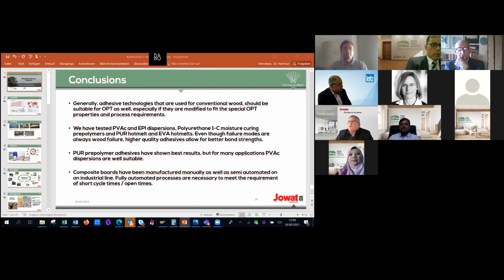So coming to my conclusions, generally, all adhesive technologies that are used for conventional wood should actually be suitable for OPT, as it is chemically a similar material. And this is actually the case. So if you're really modifying conventional adhesives, you can make them fit for purpose, to be very well suited for OPT gluing. So we have tested PVAc, EPI, polyurethane one component moisture curing prepolymers, polyurethane hot melts, and EVA hot melts.